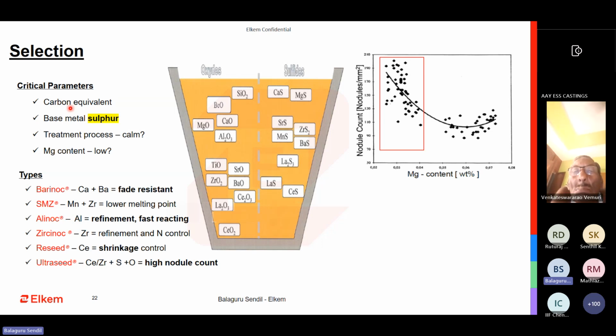Keep the correct carbon, keep the correct silicon, and then add the required inoculant. If you're going to reduce your inoculant from 0.3 to 0.1, make sure that the silicon pickup from the inoculant, which is being lost due to lower addition, is compensated in the base itself. So typically when Elkem goes and optimizes inoculant additions, we say reduce your inoculant addition. At the same time, to ensure your final carbon equivalent is the same, whatever silicon loss happens because of lowered inoculant additions, you have to compensate for with additional silicon in the base metal. So you don't overdo it or underdo it.